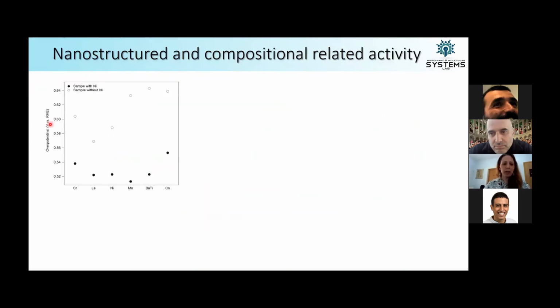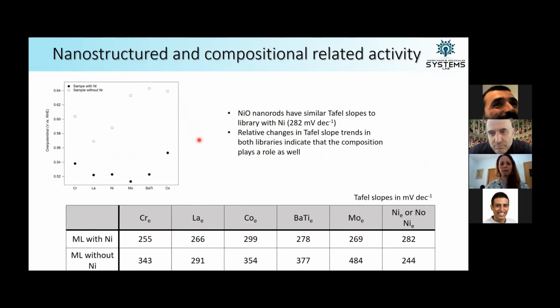And indeed, if you compare the overpotentials for the different libraries, you can see that for the sample that contained the nickel, the overpotentials were much lower, and for the sample that didn't contain the nickel, the overpotentials were much higher. So if we just compare the Tafel slopes, relative values, not full values, because we had very high scan rates for these measurements, you can see that they're very similar throughout the library that contains the nickel, meaning that the mechanism is the same. And furthermore, the nickel oxide nanorod pure sample also has a very similar Tafel slope. So the mechanism is similar, meaning that in the library that contains the nickel, these nickel oxide nanoclusters are the active component, and they are what's dictating the activity towards oxygen evolution reaction.